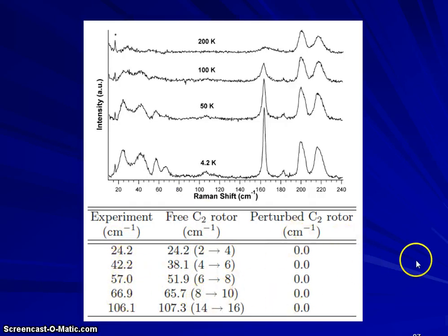We should not see those peaks if there is a rotational barrier. But we just calculated a rotational barrier of 3 kcals per mole. That should have been large enough to obscure those peaks from being visible in the Raman spectrum. However, the peaks were there and were approximately where we expected them to be.